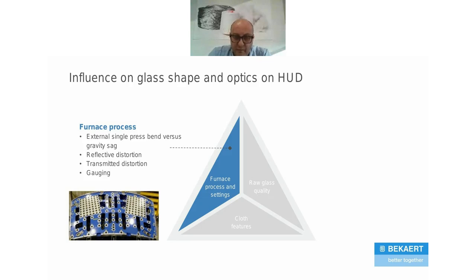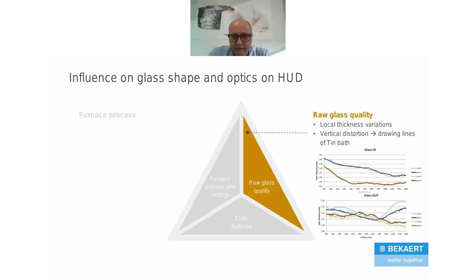Another thing is the thickness of the raw glass quality. And it's obvious that when you have scrap in, you will also have scrap out. So what is important is that your inner and your outer glass quality is perfect, and that you can also measure that to see what the end quality is. For example, we look at local thickness variations, but also at the vertical distortion in transmission, and maybe also in reflection, to see the drawing lines of the tin bath that can play a role afterwards in the optical quality, especially in transmission.